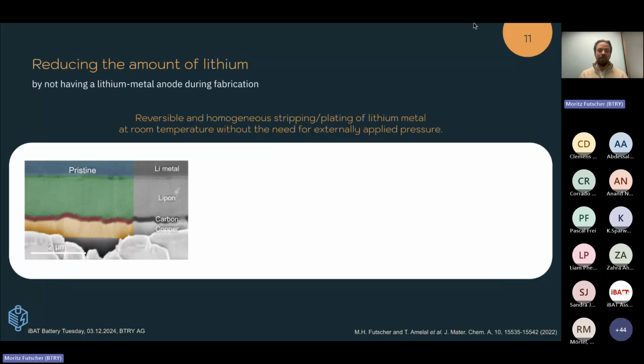Then another topic, which is the anode-free design. This is also a topic which is often addressed in bulk solid-state batteries. So why do we want an anode-free design? First of all, having a lithium metal anode in the fabrication process complicates things quite a lot, because lithium metal is very difficult to treat, handle and fabricate, and it needs very clean environments. On top of that, ideally, you would have very little excess lithium metal in your batteries. So one way to do this is to fabricate an anode-free design, which means that there is no anode present in the fabrication. You only fabricate a cathode, a solid-state electrolyte, and then directly the current collector on top. And this is more or less what is highlighted here.